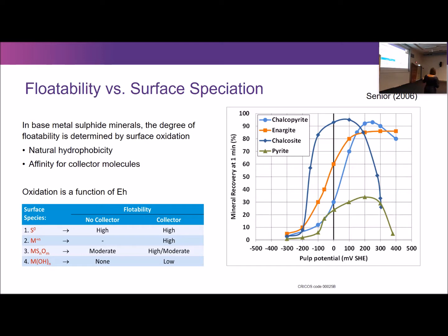So what happens? Initially, when your pulp potential is very low and you have completely reducing conditions and no oxidation takes place, none of the minerals exhibit any floatability at all. Then as you progress to slowly more oxidizing conditions, the floatability sharply rises, reaches a peak, and then drops off like a rock. This behavior is different for every different mineral type. Mind you, these were done individually and not with mixed couples, so you will not expect the exact replica of this behavior in a real system. But this difference is there because of the difference in the chemical activity of each of these minerals.